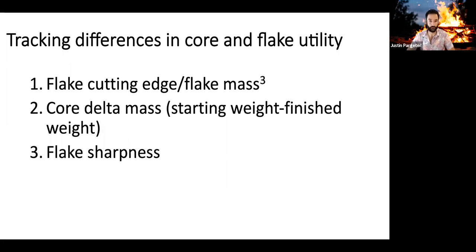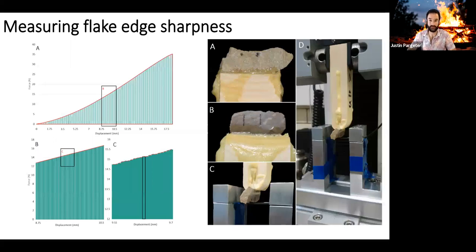And last, we investigated the sharpness of unheated and heated flake edges using an Instron universal testing machine and a standardized hafting protocol. For the sharpness test, I selected 30 flakes from each heat treatment condition. These flakes were then sent to Alistair Key, who was kept blind as to each flake's heating condition. We attempted to control for edge angle at this initial flake selection stage by selecting flakes with edges of around 30 degrees. Subsequently, Alistair identified the most homogeneous 10 millimeters of length for each cutting edge for use in the controlled cutting tasks. These tests involved measuring the force, work, and displacement necessary to cut a PVC pipe using hafted, heated, and unheated silcrete flakes.